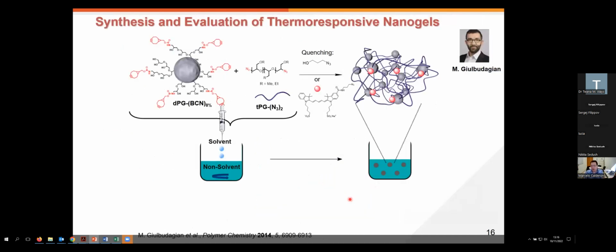Another methodology that we use for the synthesis was nanoprecipitation. Here we pre-synthesize the cross-linker, and then we also pre-synthesize the thermoresponsive polymer. So here we have better control over the length of the thermoresponsive segment. We functionalize at the end. We make these telechelic polymers, and then we play with the nanoprecipitation here.